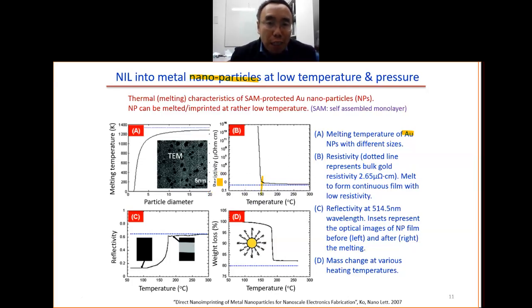But this one is the resistivity. So you have the gold nanoparticles. They heat up to 150 degrees. Then the gold nanoparticles get connected, merged together to form a continuous film. And when you form a continuous film, you get low resistivity and also a very high reflectivity. You form the gold film at this temperature. For the last example here, we have the gold nanoparticles, but with a ligand, the RS group. We heat up to nearly 190 degrees, and this RS molecule is dissolved. You have the weight loss.